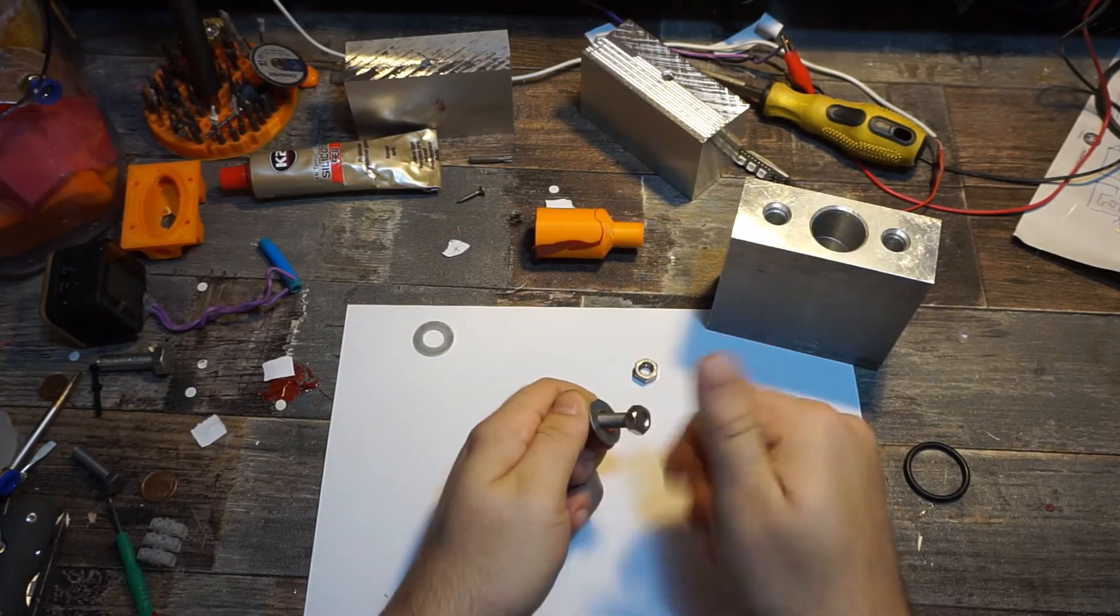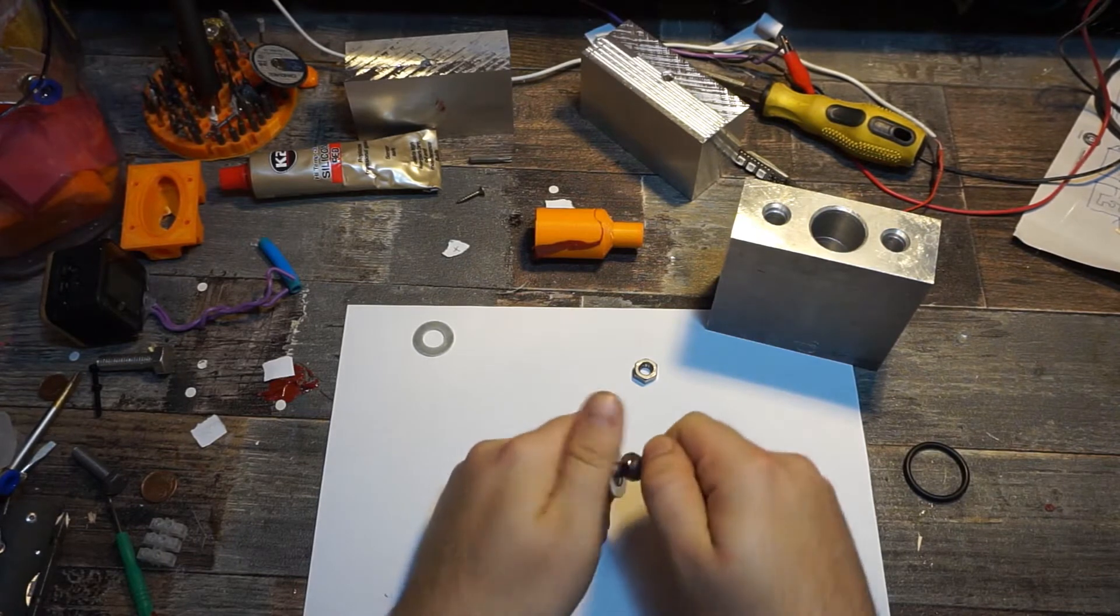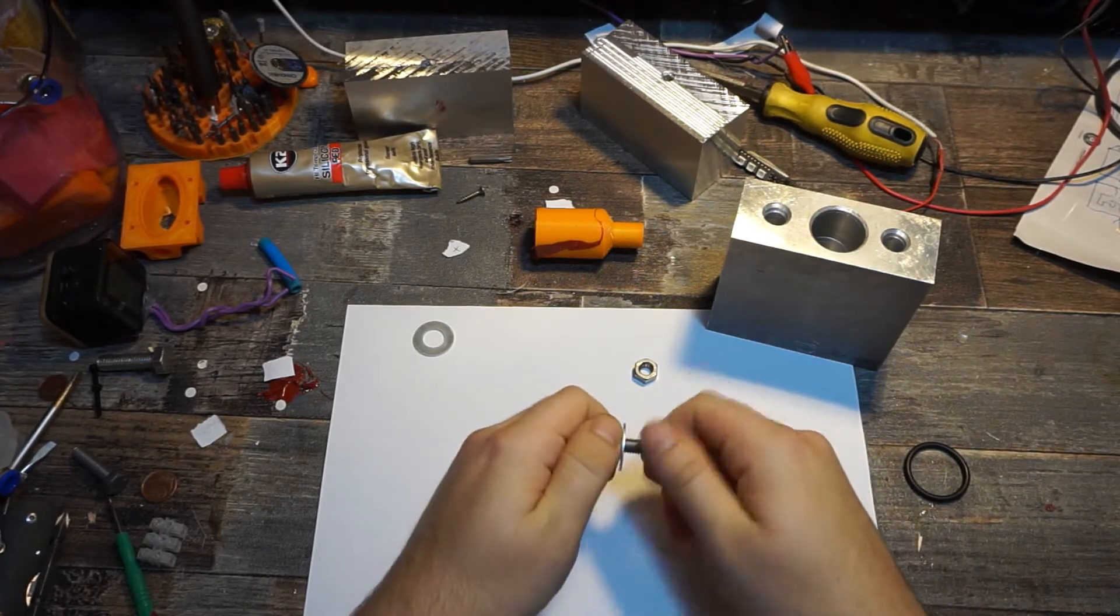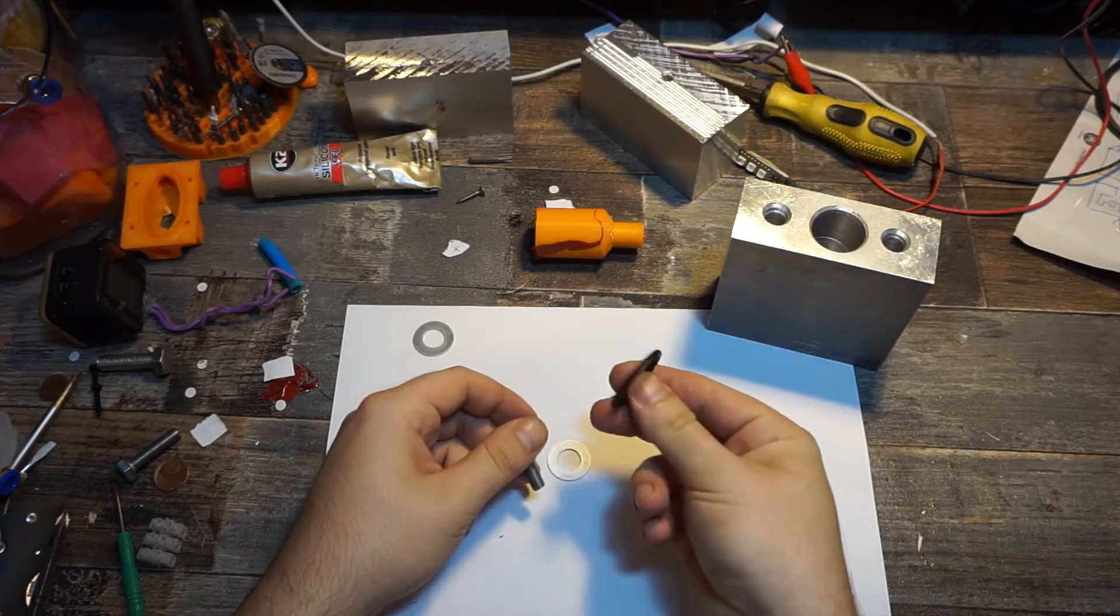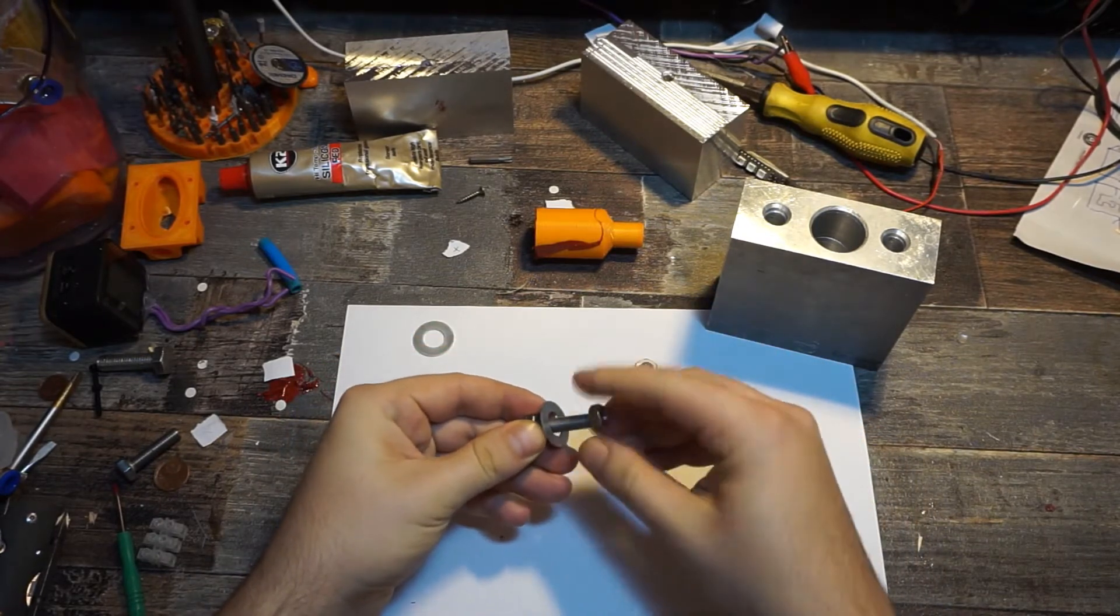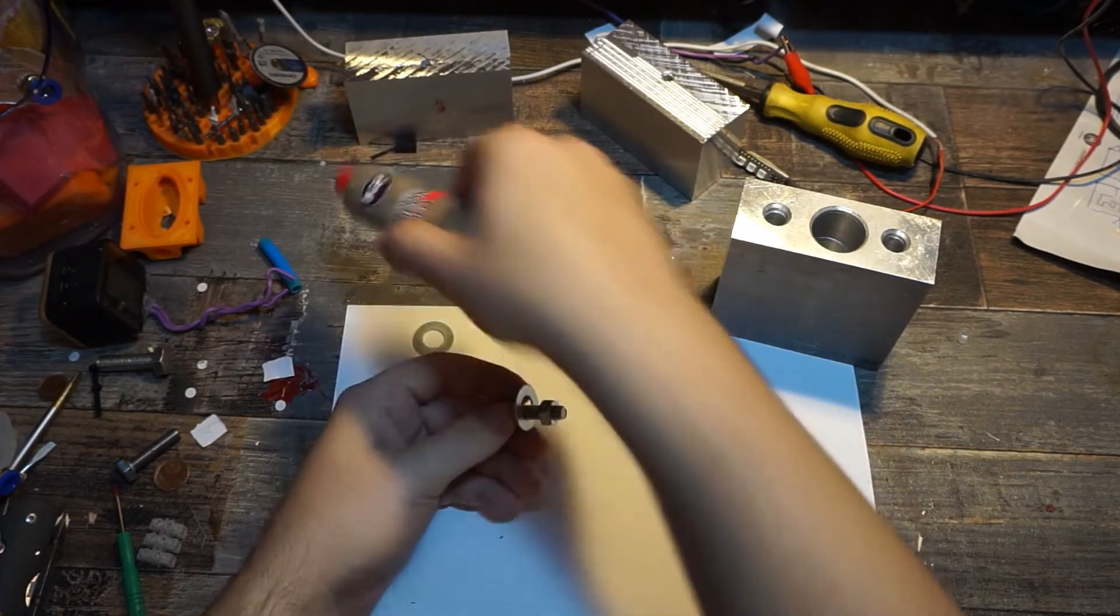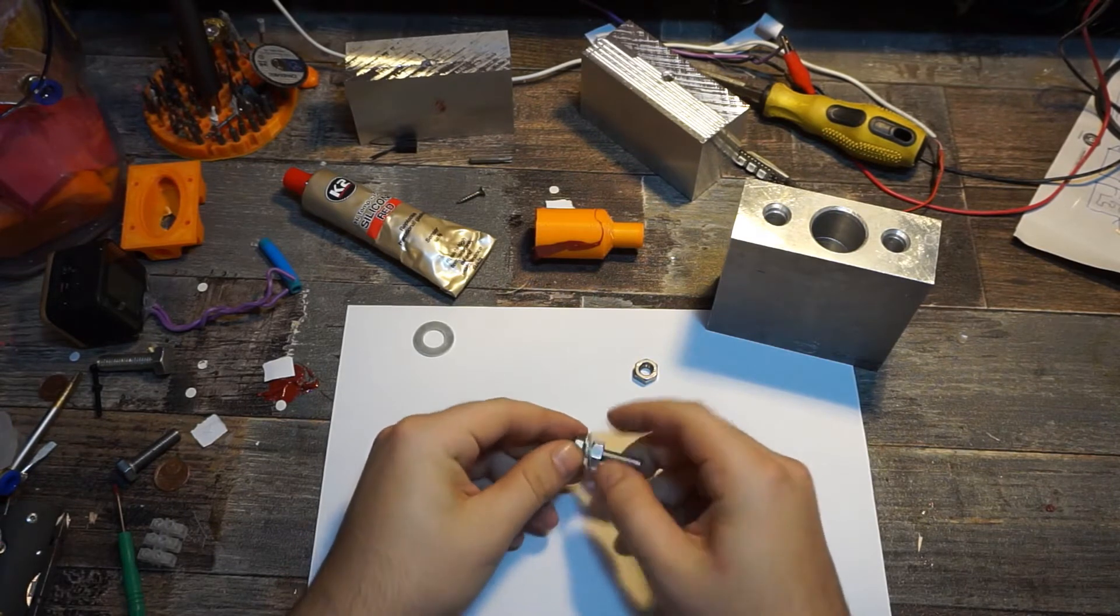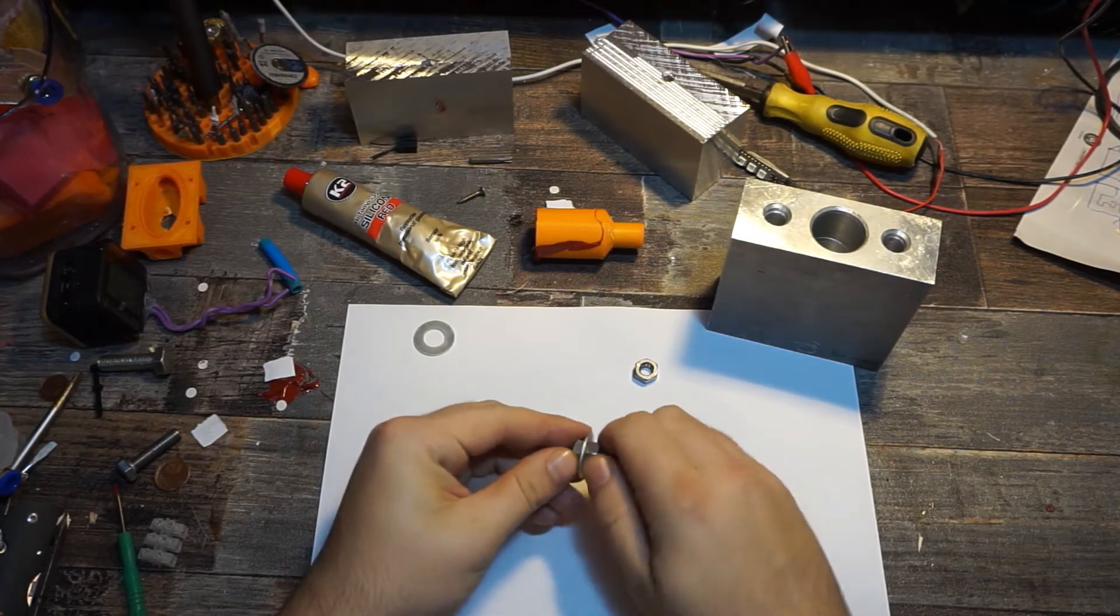I need some kind of rubber sealing that I can press into it, and the problem is the whole thing will get like 250 degrees Celsius hot. That's too much for the most materials I would normally use, like o-rings—they can't manage the high temperature. That's why I decided to try something out and use high temperature silicone. It's rated for up to 350, so that should not be a problem. I actually tested a little bit of it before just using my soldering iron and setting up the temperature, and the silicone did absolutely fine.